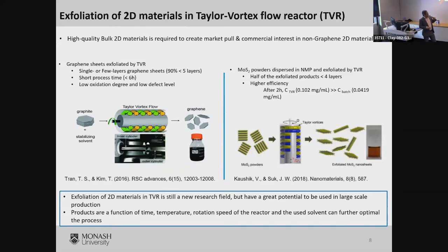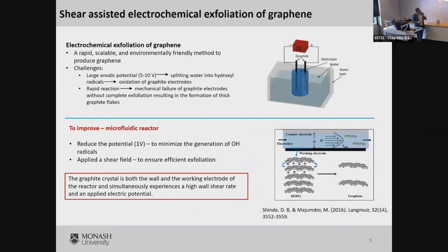So this is a paper published in RSC Advances, which looks at exfoliation of graphene materials in a solvent. And then again, people have used the same kind of technique to convert molybdenum disulfide into MoS2 flakes. They've reached reasonably high concentrations of these materials. So technologically, it is possible to use flow reactors to synthesize this type of 2D materials. And it is a relatively new research field, but has great potential to be used at large scale. I'll talk about some of the innovations we are thinking about in this technology. Products are a function of temperature, time, rotation speed, etc., and a wide number of solvents can be chosen.